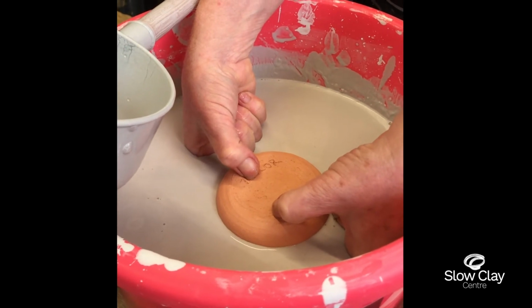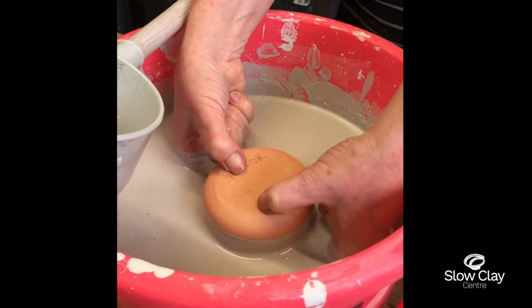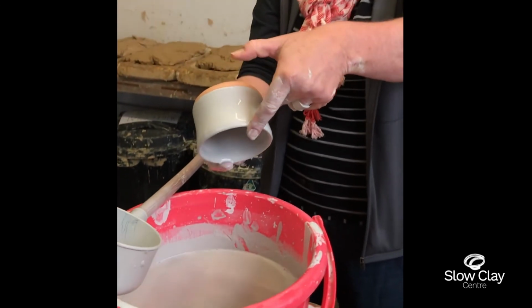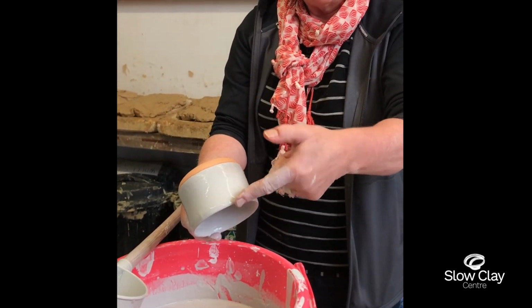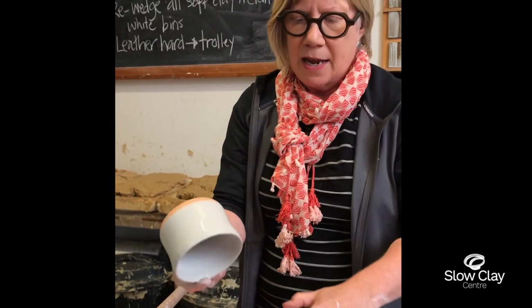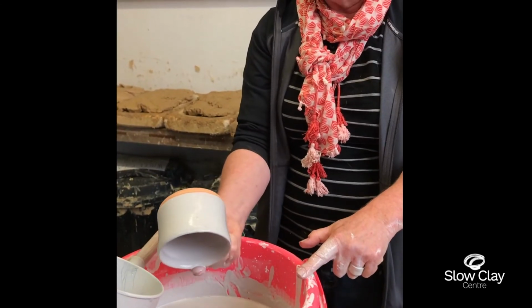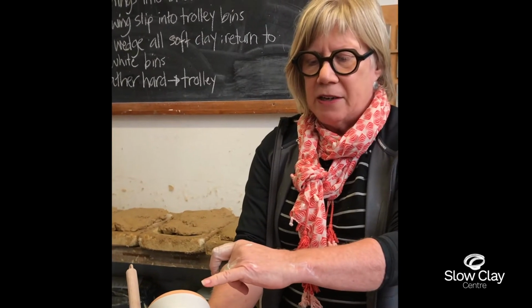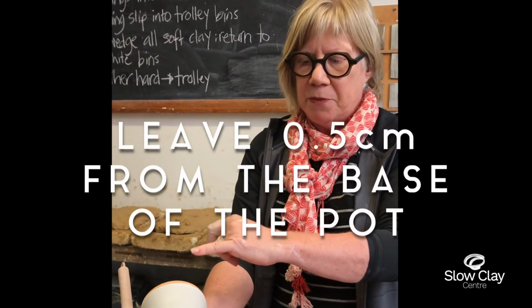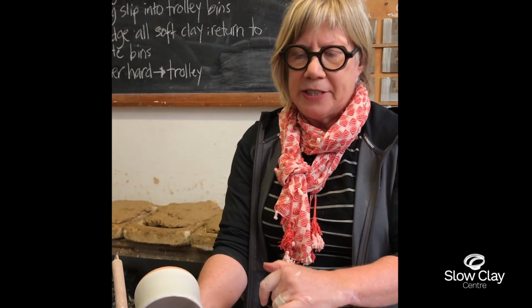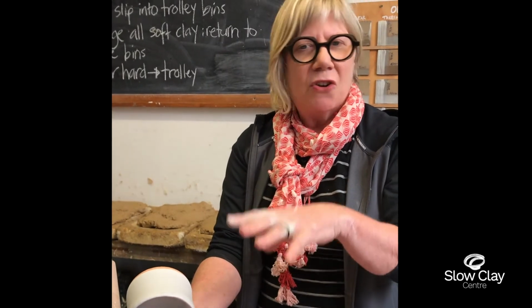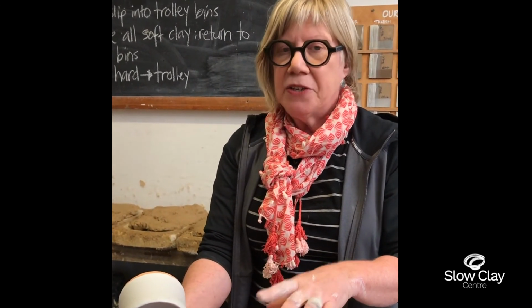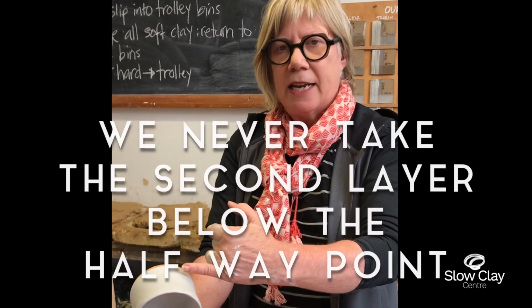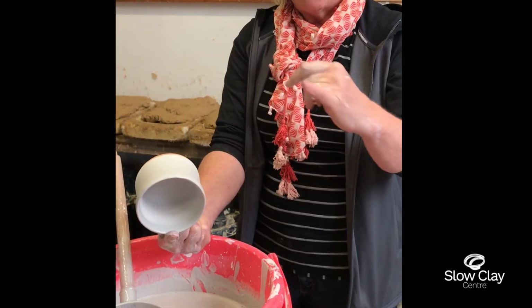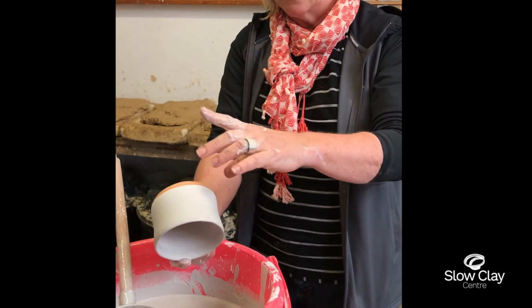1, 2, 3, 4, 5, and out again. And then this time I'll angle it, touch up the rim, angle it onto one index finger while I'm waiting for it to dry. We usually like to leave a good half centimetre from the base of the glaze to the base of the pot, and that just means if it does run a little bit, it's not going to run off the pot. And we definitely do that with the second layer. We never take the second layer below the halfway point. So when I move over to the black bucket, I'll demonstrate that.